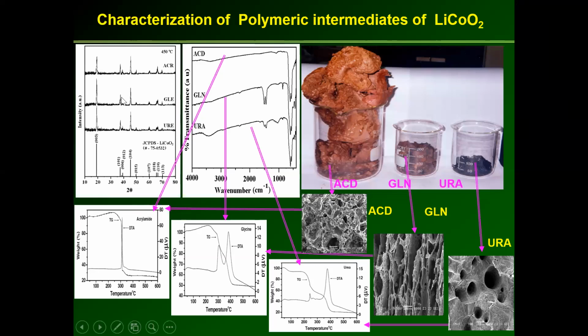That's what we observed, in XRD and also FTIR. In FTIR you can also see the pure compound, whereas in the others one part is increased, so something is formed, and again one part is evaporated, giving some other complex. So you can see multiple phases, multiple structures. These are not good. This one is the only good one, with fine particles and a pure compound. So from this we can understand.